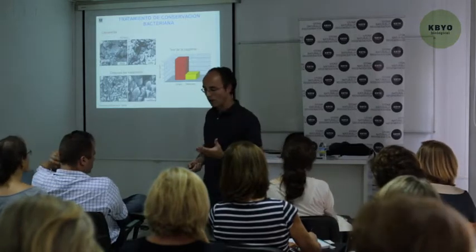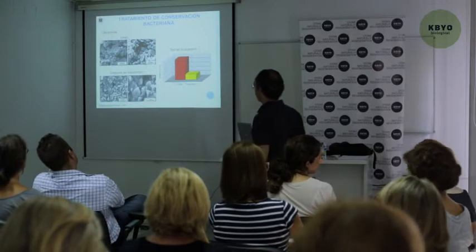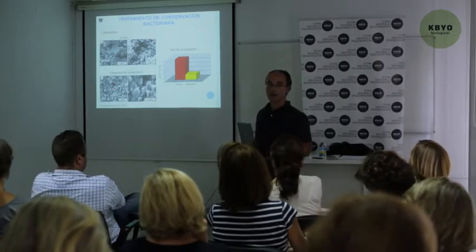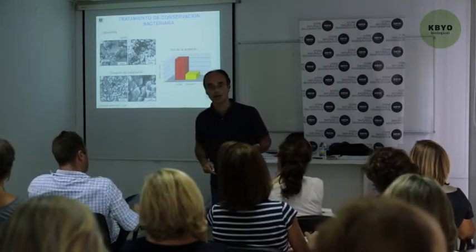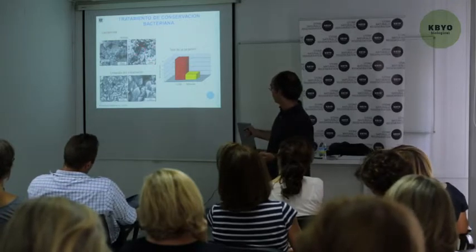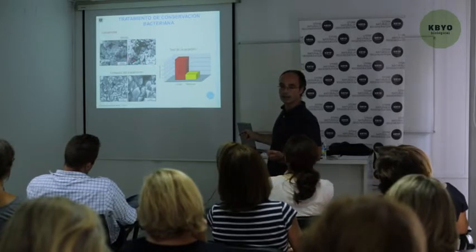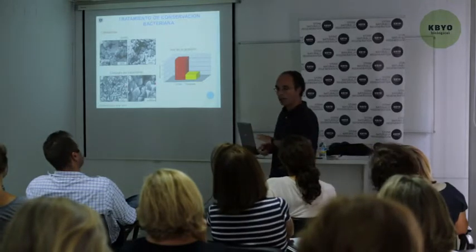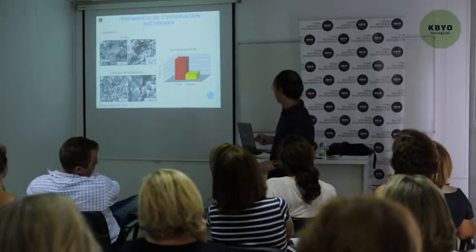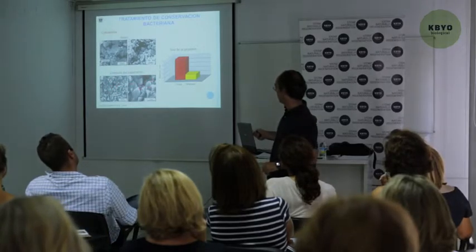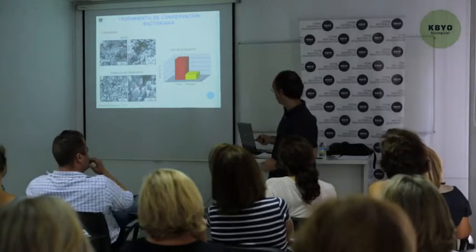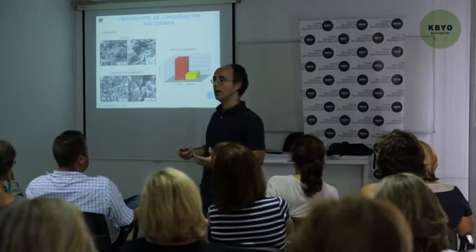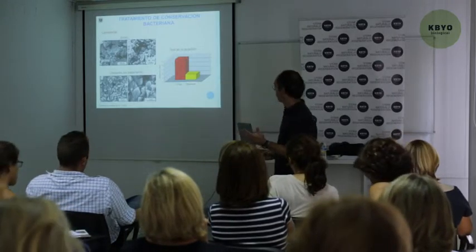It is a new material that consolidates the original material, as can be seen in tests by the simple and reduced test of stickers. This system consists in applying a sticker on a material before the treatment. When we strip off the sticker, we check how much material remains on the sticker from the surface. If we do it in many places, we will get a statistic of the quantity lost on the surface. After the treatment, we put the sticker again and check how much material is lost. It is quite similar to what any restorer does when he sees a material and scratches it a bit with the finger.